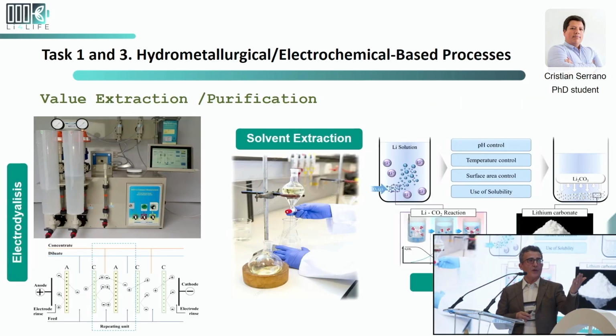And for the PLS, we're using different purification techniques, from solvent extraction to ionic liquid, and we're also using direct carbon dioxide injection into the system to produce the lithium carbonate, and we also use electrodialysis. The idea is to improve the efficiency and selectivity of purifying the PLS and selectively precipitating or separating the lithium in the form of lithium carbonate, which can directly be used in batteries.